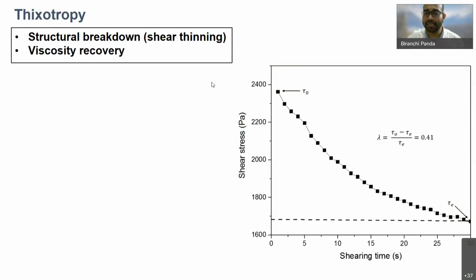So what happens in the shear thinning process? We take a bulk of material and apply a high shear rate to see what happens to the shear stress. For the material we printed, we can see that once you apply a high shear rate, the shear stress comes down to a very low value. It gives a factor of lambda, which is around 0.41. It says that the material is very good for concrete printing application, because as soon as you apply a high shear rate, the viscosity or the shear stress goes down to a very low value.